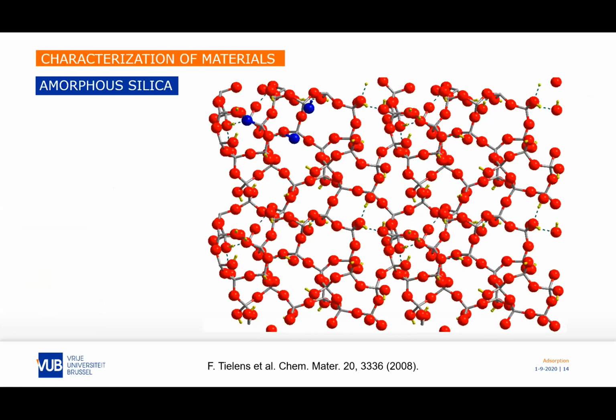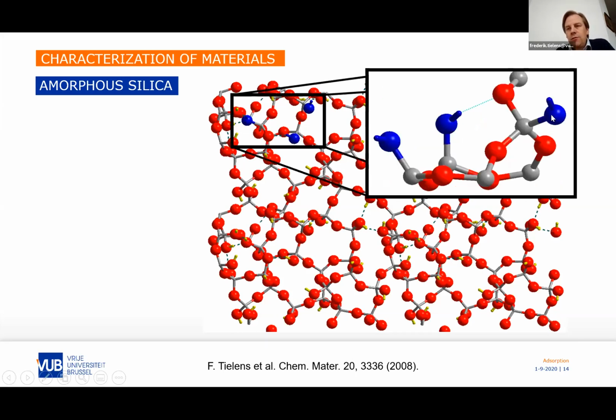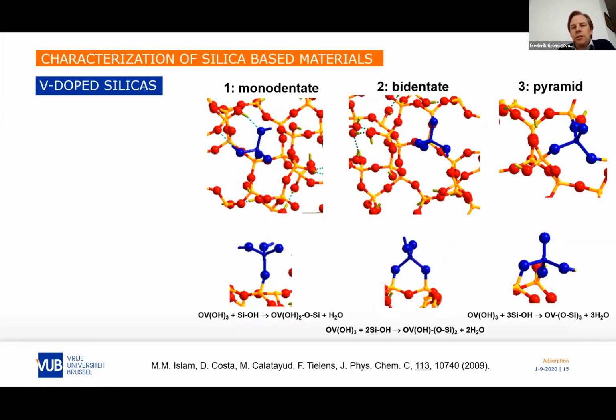So first of all, if you want to graft an oxide, or here in this special case, monomer mono-oxide species, we need to find a grafting spot. And this is typically a spot where we have a high density of silanol sites. What I show here is the site where you have three silanols close to each other. We are in fact ready to accept the presence of a transition metal oxide monomer. On this site, which is also called a silanol nest, we adsorb this kind of species.